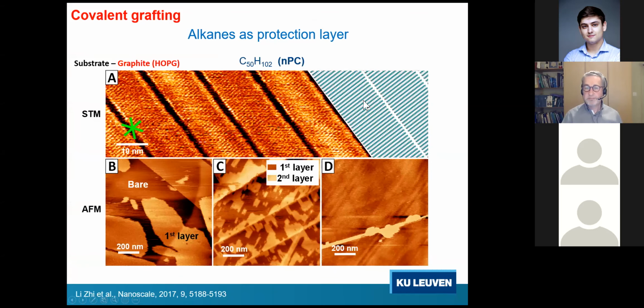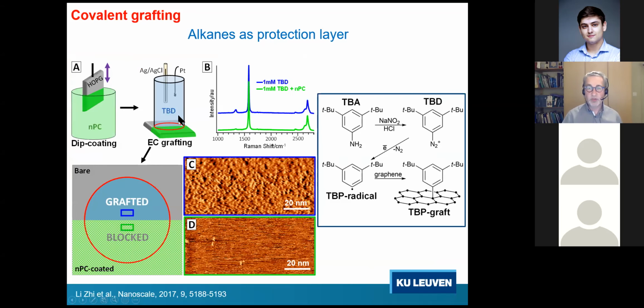If we now expose such a layer to the radicals that we can generate, for instance, electrochemically, these are the radicals that I have talked to you about. The question is, if you have just one layer of these alkanes, and the alkanes are lying flat on the substrate, not orthogonal, will this be enough to protect the substrate from radical attack? And actually it does. This is the covered area, so an alkane covered area of the carbon substrate. This is a non-covered area, and you clearly see the difference in density of the grafted molecules.